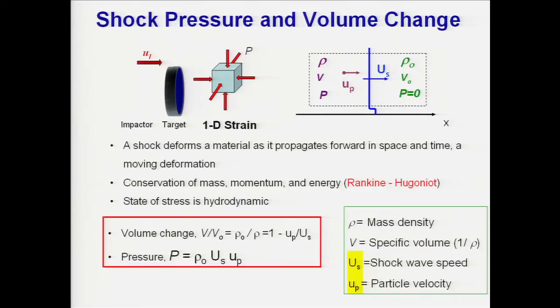So there are two simple ideas which I want to introduce. One is associated with the volume change. When the shock wave is moving through the solid, it sets the solid behind the shock wave in motion, similar to when you have collisions. And that particle velocity is U sub P. That is related to the amplitude of loading, how fast I'm impacting the solid. And one can calculate the volume change or the change in density through this very simple formula. That's the ratio of the particle velocity to the shock wave speed that will give you the volume change.